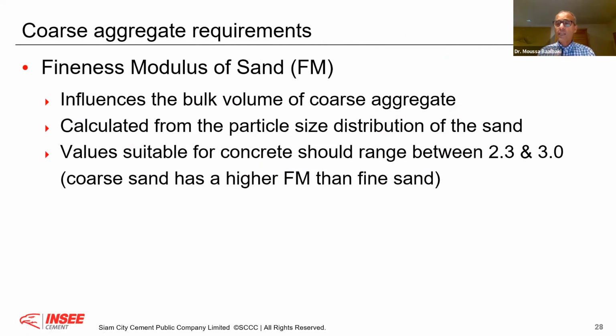Now, there is one important factor from the sand that will tell you how much coarse aggregate you need, which is the modulus of fineness of the sand. Okay, in the European countries, they do not use very often the modulus of fineness of the sand. But if you look at the ACI, the modulus of fineness gives you to understand how fine is your sand. And normally for normal concrete, between 2.3 and 3 modulus of fineness is a good number. Therefore, if I have a fineness modulus below 2.3, it means my sand is too fine. It's too fine. Or if it is more than 3, it means the sand is too coarse.